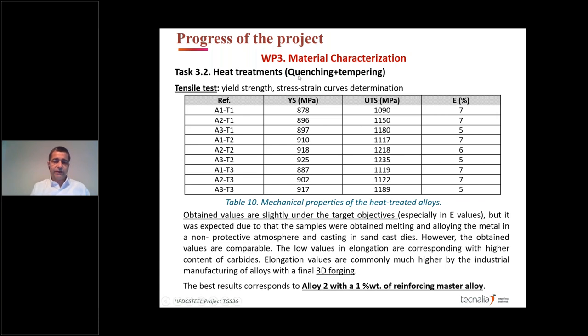After that, we also have the mechanical properties. We can see here the ultimate tensile strength for A1, which is the one without master alloy, A2 with 1%, and A3 with 4%, at different temperatures. We see low elongation values, but good yield strength and ultimate tensile strength. This is related to the fact that these trials were done at Tecnalia with a semi-industrial process, and we don't employ 3D forging. So we think these values were good enough for the industrial validation of the alloy. So we select alloy number 2 with 1% of the reinforced master alloy.